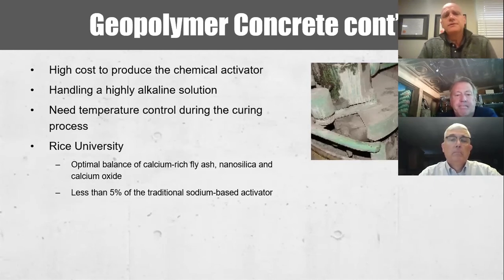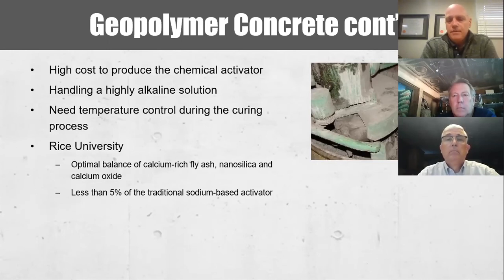What's really promising is the latest research out of Rice University. They studied all sorts of different fly ashes and slags to be able to optimize the use of sort of calcium-rich fly ash and nanosilica and calcium oxides to be able to use less than 5% of the traditional sodium-based activators, meaning that now you can make concrete with a lot less of the activator, which brings the cost way down, plus the ability to handle that caustic material to a point where it may be commercially viable. So this is something to be looked at for the future.